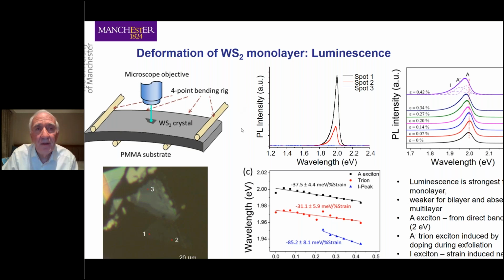And if you now deform the substrate, then these luminescence bands shift, and they shift just like the Raman bands shift, and they shift linearly. So if you deconvolute the luminescence band, you can see that this is now the peak position of the luminescence band against strain. We get large shifts again. So we have the essence now of a strain gauge and a strain measuring system.